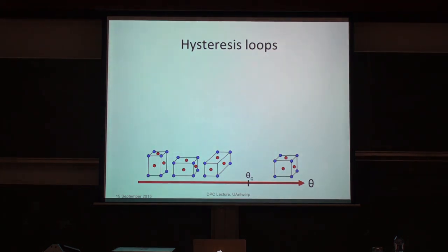But anyway, the general type of phase transformation I'll discuss is really one of the most simple kind. It's phase transformation from one crystalline structure to another. This is a very simple example. We have a cubic, face-centered cubic type structure in which it elongates along one of the 100 directions. And then, of course, by symmetry, it could elongate along any one of those directions. And so you get three possible variants of the low temperature phase. In fact, they're called variants.